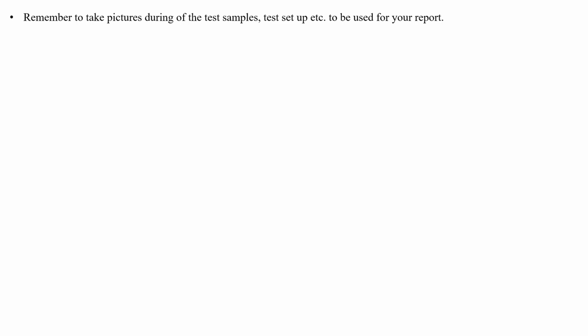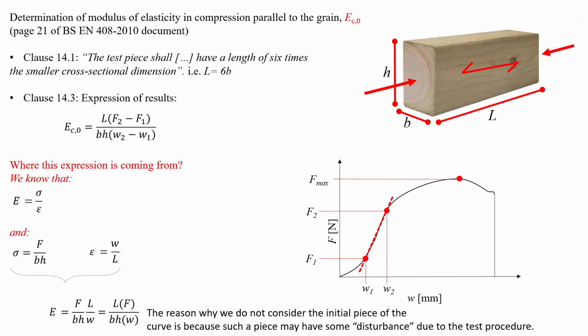However, we're going to be putting on tiny amounts of load. The Zwick, the machine that they've got downstairs, is about 150 kilonewtons. It can do massive loads. So this is a tiny amount. And as our sample is getting the small load being applied, that first part there'll be settlement. If I don't cut that surface perfect, and my point that comes down on it is not perfect, there'll be settlement. So that's what we're seeing at the start. We're going to ignore that first 10%.